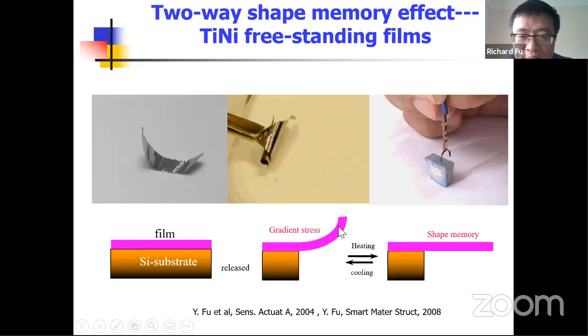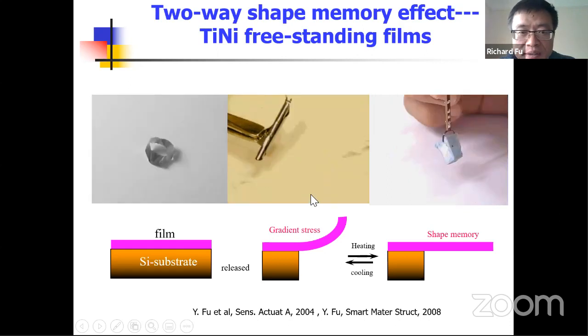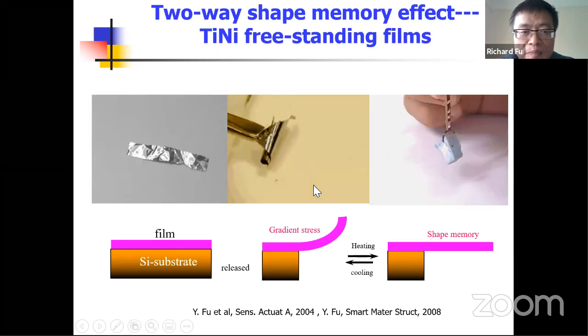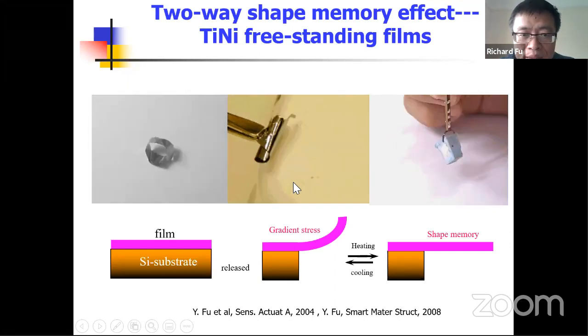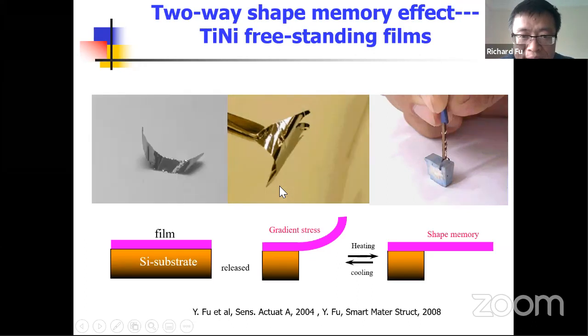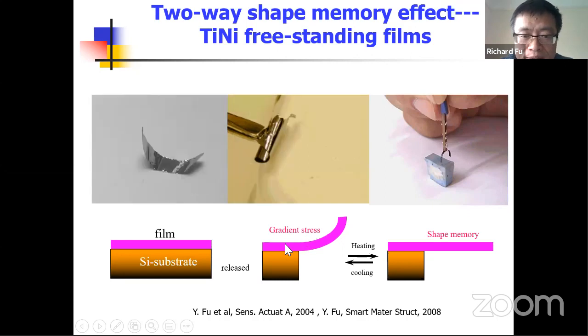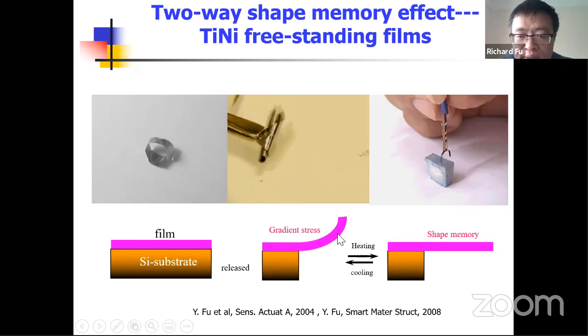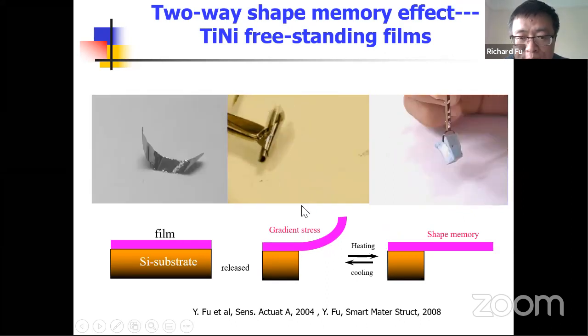Of course, shape memory alloy thin film is actually very easy to obtain. We just use the sputtering method to deposit titanium nickel and control the composition, which is 50 titanium, 50 nickel. Because it's a metallic film, the film is very ductile if your deposition condition is very good. And then it can be peeled off from the substrate totally. After peeling off, the freestanding material has a gradient stress in the film, because during the deposition, there will be a gradient change of the composition of the film from bottom to top.